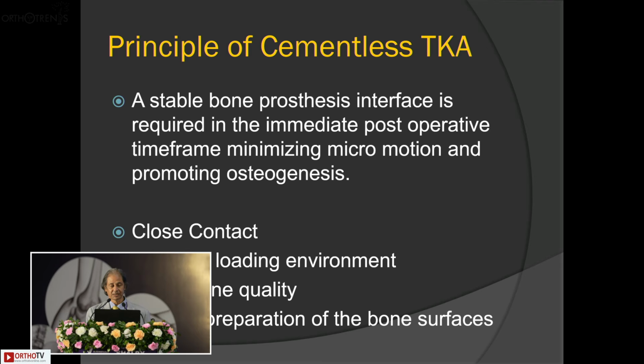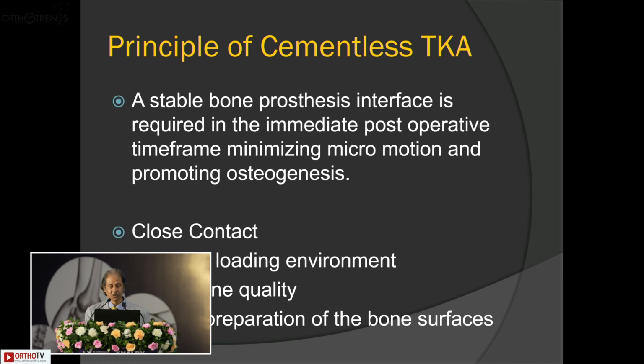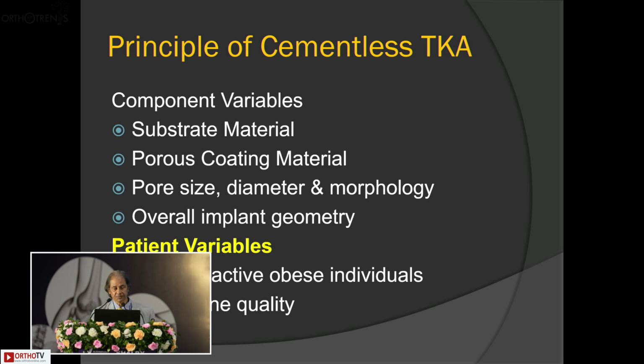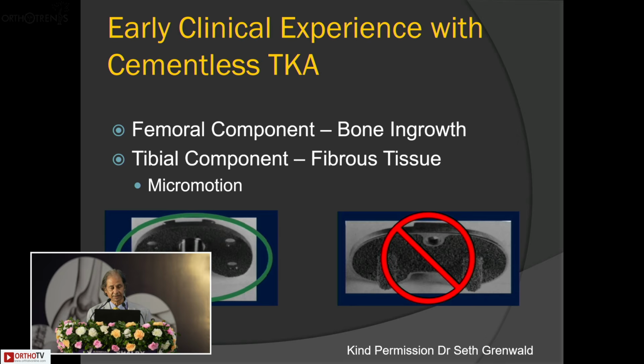You need a stable bone prosthesis interface with immediate post-operative friction fit and a surface that minimizes micromotion and promotes osteogenesis by close contact, dynamic loading, good bone quality, and precise preparation of bone surfaces. And the principle is substrate material, porous coating material, pore size, overall implant geometry, ideally in young active patients. Obesity is not a contraindication, and good bone quality.